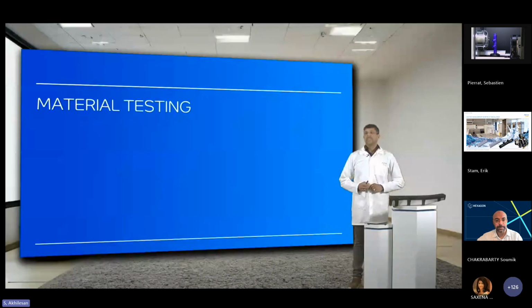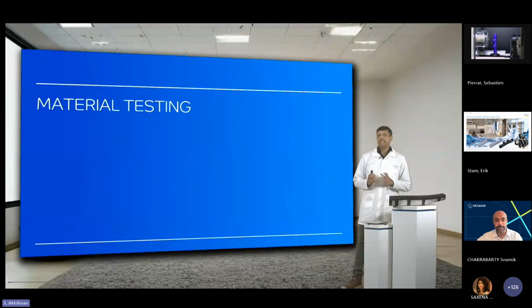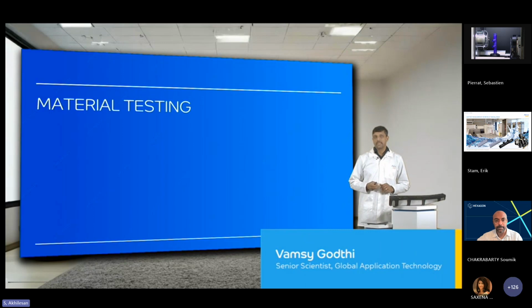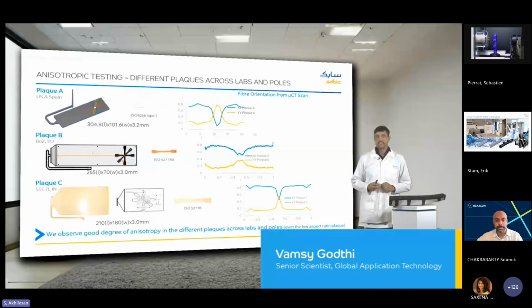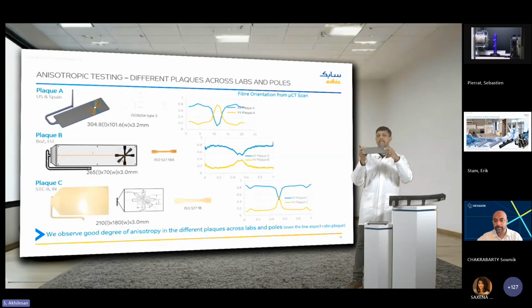Thank you, Subhranshu. With this note, let's begin by looking at what all it takes to characterize the anisotropic properties of fiber-filled thermoplastics. The whole process begins by injection molding a shear plaque. A shear plaque is nothing but a flat plaque, a 2D geometry with a gate at one end. With this, we fill the part, and towards the end of the fill, we expect aligned fiber orientations in the direction of the flow. And this is the first step in the process.